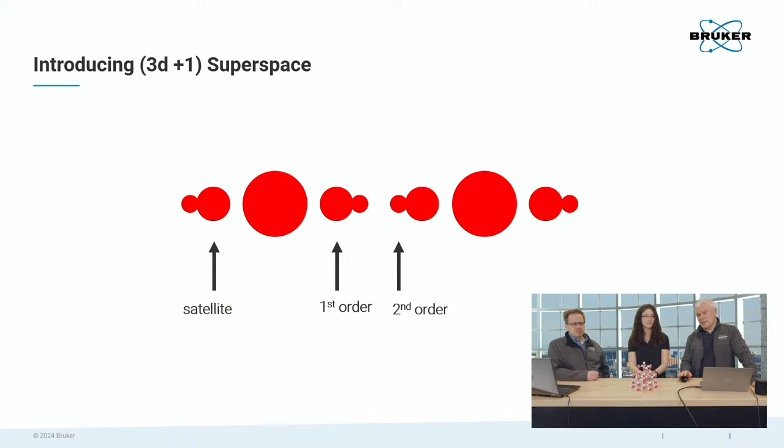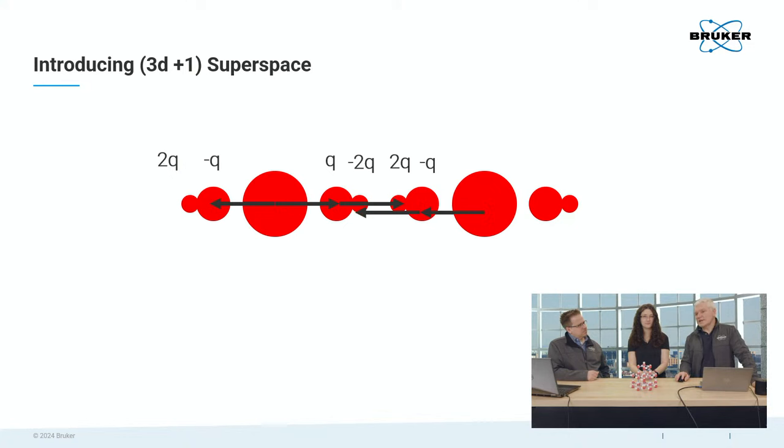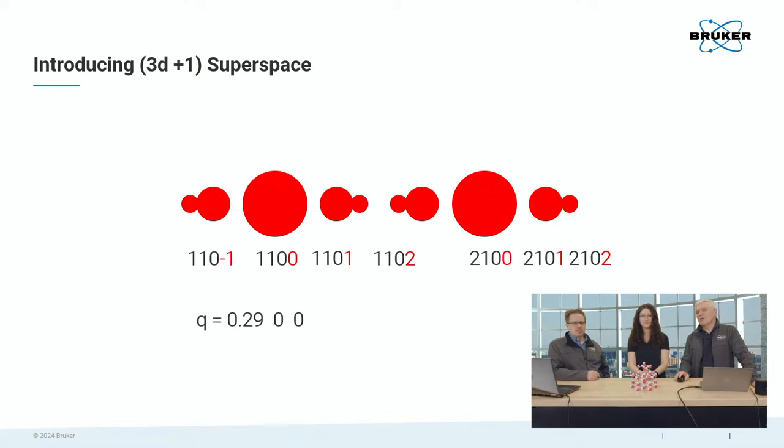So now you have a satellite, and it has a little satellite, but that satellite does not belong to that satellite. So when you say first order, second order, this is how this looks. Now look at the arrows. You see, although it's really close to Q, this is actually a satellite at negative 2Q from the neighboring reflection. Okay? So now what we can do is, with one additional Q vector, we can describe or index all these